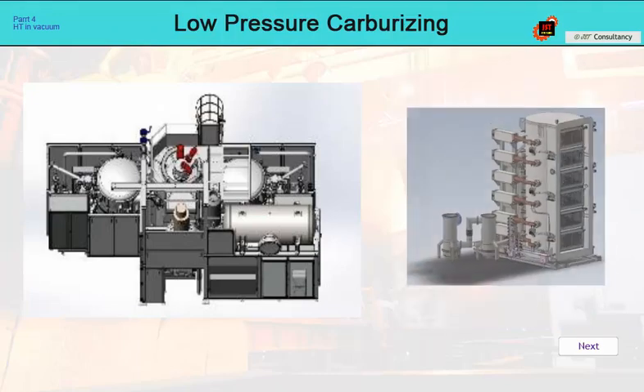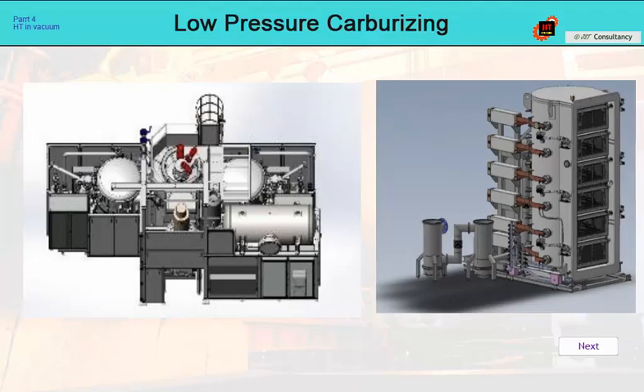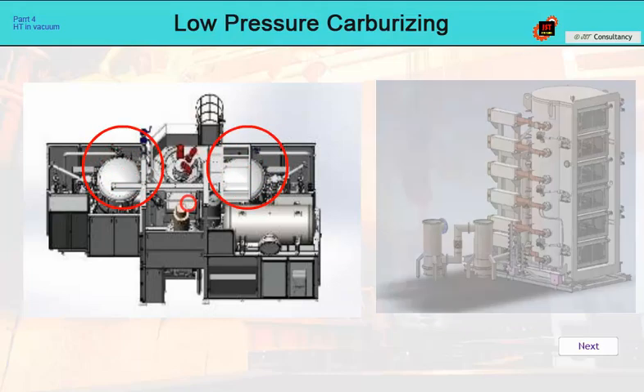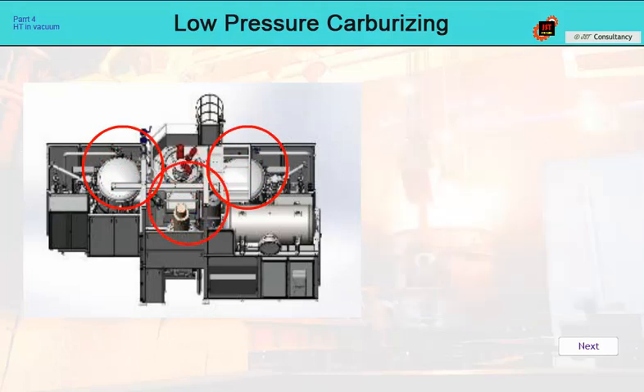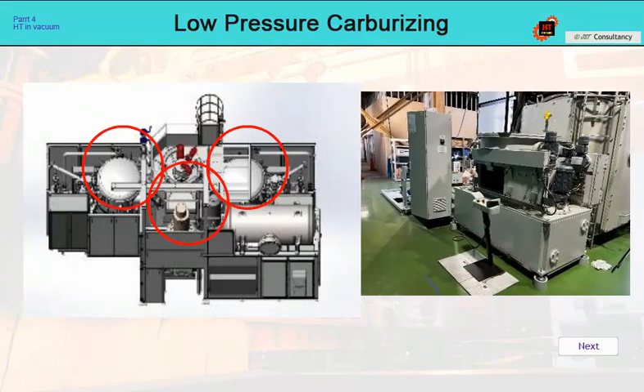The basis is a vertical transport chamber with 4 free positions for installing the device. 2 positions are occupied by columns with heating chambers. The third position is a quenching module. If the Nano is with oil quenching, the load cannot be placed through this module due to possible contamination of the heating cell with oil. It can only be taken out of the furnace after quenching.